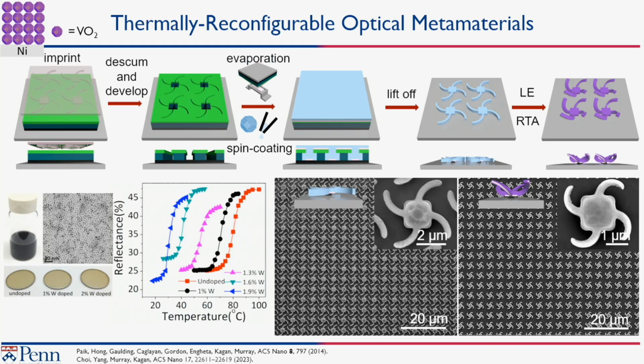So one of the things that we did is that we also had, many years ago, worked on vanadium dioxide. In Chris Murray's lab, they developed the synthesis of VOx, a precursor to vanadium dioxide. So you could synthesize these materials. We heard about VO2 earlier this week. And so you can see that at room temperature, VO2 is an insulator. You see that electrically. You also see it in its reflectance. When it's an insulator, the reflectivity is low, like you think. And then when it goes through the insulator to metal transition, the reflectivity is high.